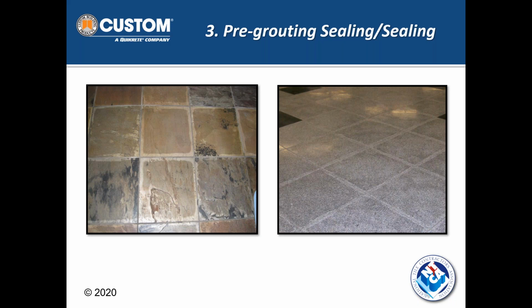Now you don't see that, it's not evident, you can't tell that happens, until you put a color enhancing sealer on it and say, wow, why are the edges not darkening? Well, they're not darkening because there used to be moisture there that contained polymer from the joints in the grout. And in essence, it becomes a sealer.